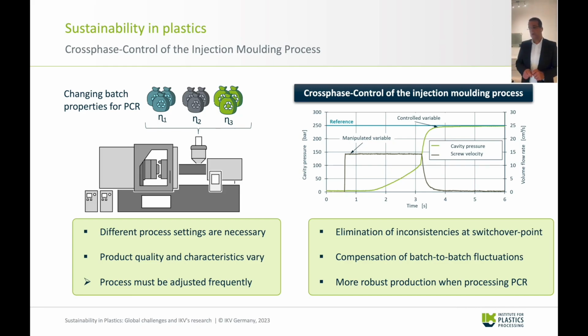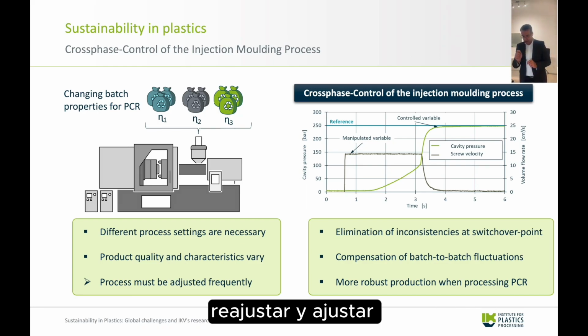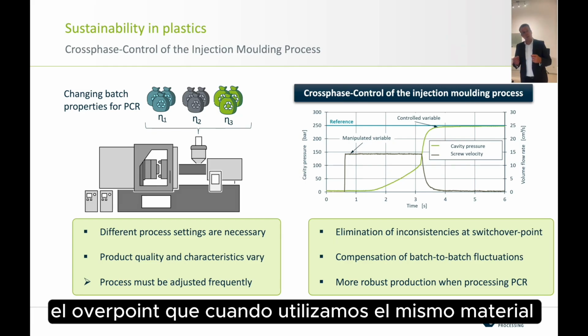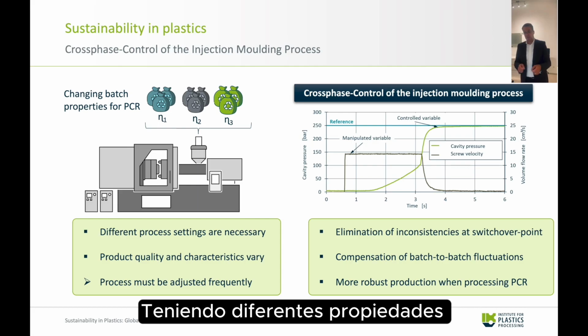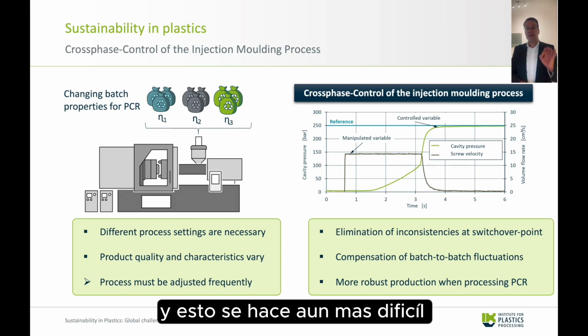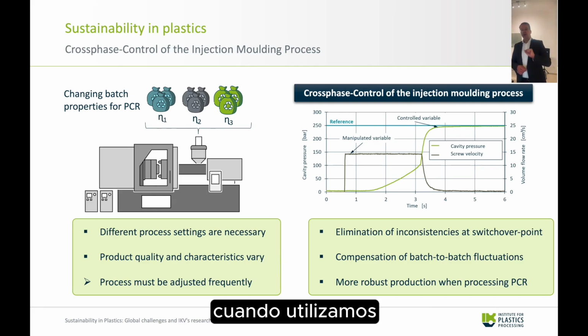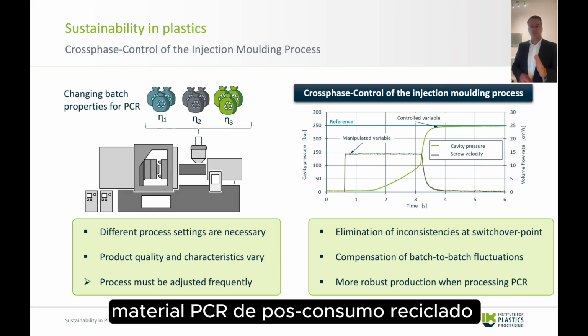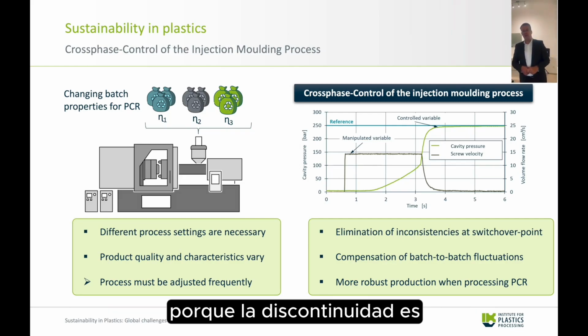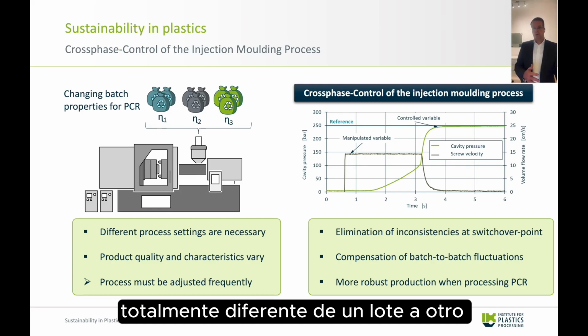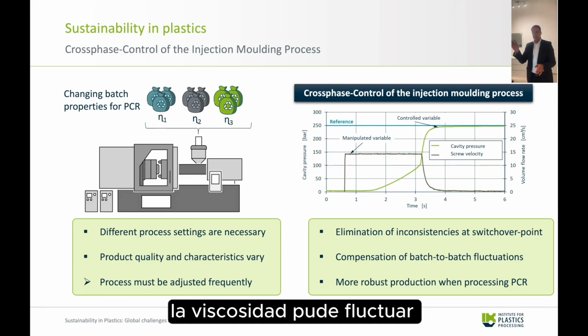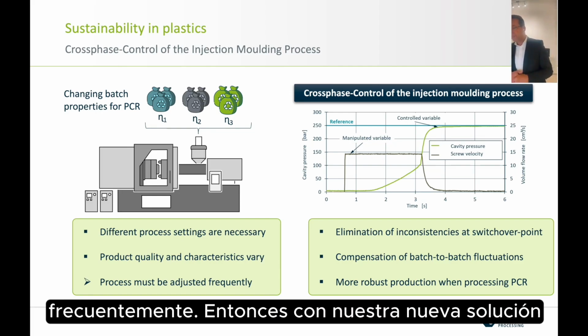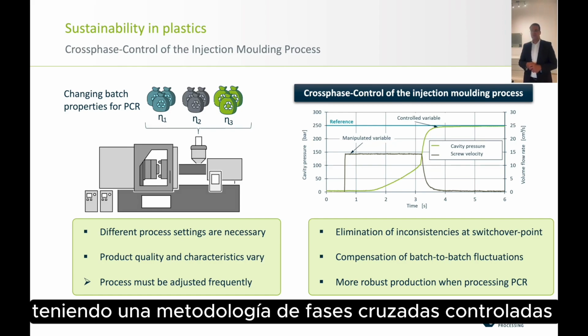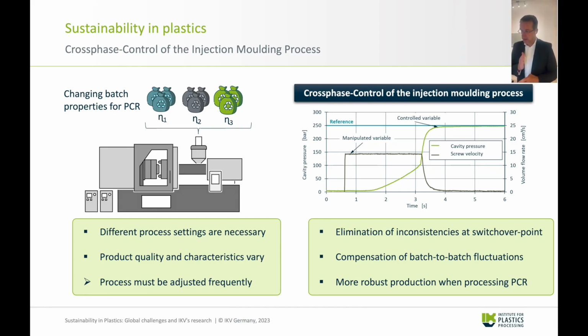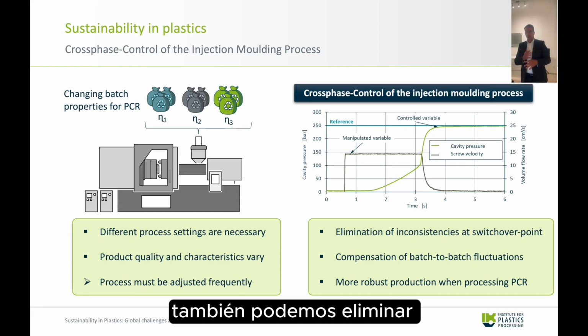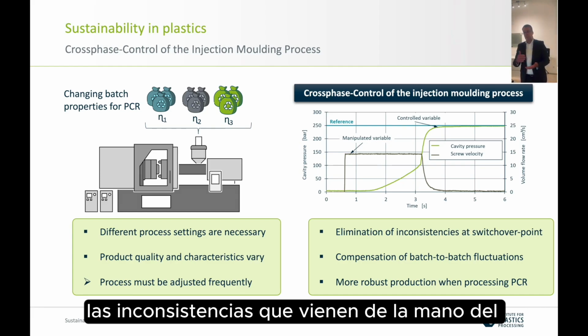And specifically, we need to adjust the switch over point when we use the same material but different lots having different properties, in particular different viscosities. And that is getting even more difficult when we use PCR, so post-consumer recycled material, because the viscosity is totally different from one lot to the other, and also within one lot, the viscosity may fluctuate frequently. So with our new approach, by having a cross-phase control methodology where we do not have a switch over point, we can also eliminate all the inconsistencies which come along with the switch over point.